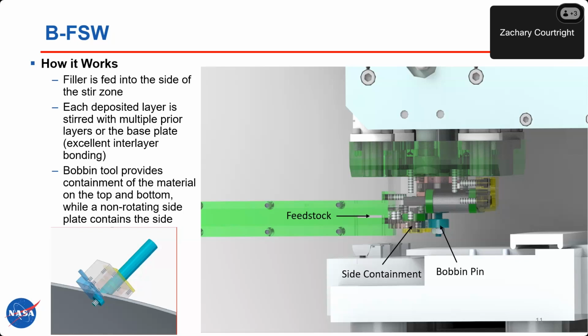But that was just lab scale. Theoretically, you could get to the point where your deposition is at least half of the diameter of the pin tool, which for a 1 inch pin tool would be 1/2 inch per pass. So there's definitely a lot of potential to increase that further. But again, like Joseph said, the surface finish is very smooth. You get basically a friction stir finish along the whole surface of the print, and it would not require any form of machining.